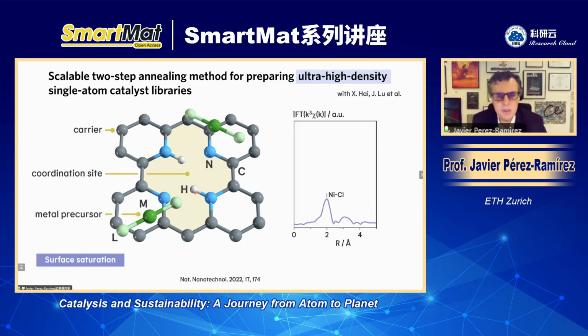So the first thing we do is actually we put a lot of metal because we want to increase the metal content, right? So we put a lot of metal, and I illustrated this with nickel chloride. So this is nickel in dark green, and in lighter green is chloride. So that's a nickel precursor. You can see here the EXAFS spectra of the deposited catalyst, where we only see bonding between nickel and the chlorine in the nickel chloride. So we put much more metal than coordination sites we have.